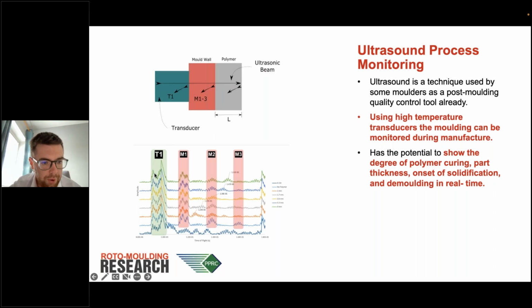So in the graph underneath here, what you can see is this T1, which is what we call the initial bang, which is the returning signal from the end of the ultrasound transducer. The sound wave then passes through into the mold wall, and you get a returning echo M1, M2, and M3. If you place a polymer plate on the back of that mold wall, there is a signal identified, which is these little numbers here that sort of increased in time across the graph.